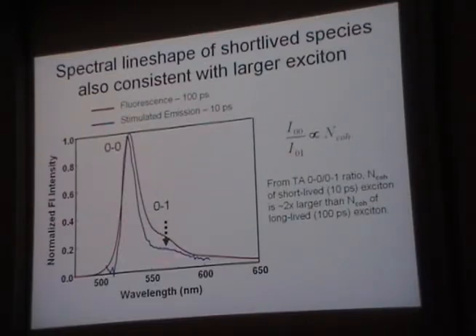There's very little 0,1, and to be honest, just the way this data is plotted, it probably overestimates the 0,1. But at least a factor of 2 less of the 0,1 peak. Again, that's our other weapon to estimate coherence length. So whatever we're seeing in the first 10 picoseconds, it's big, it's fast decaying, and it's more delocalized than what we were pulling out of our picosecond fluorescence measurements back in 2004.